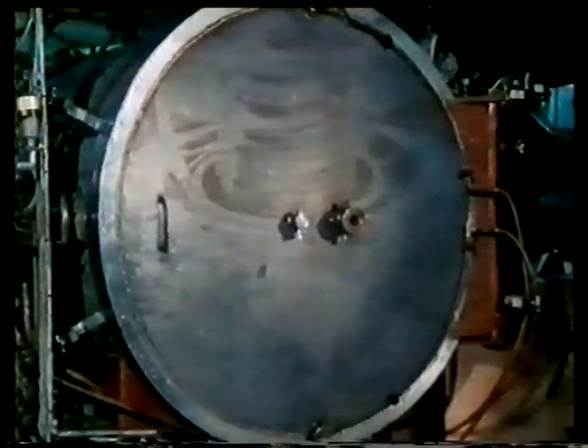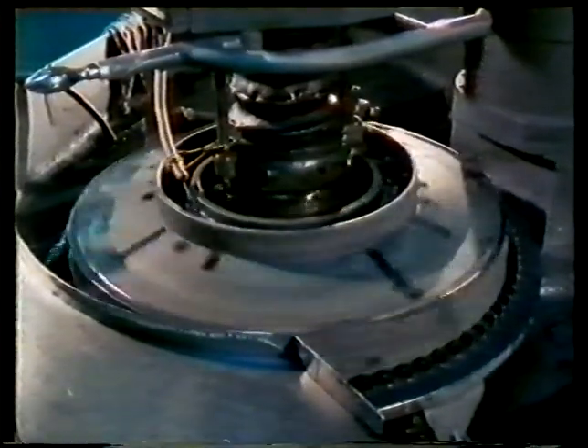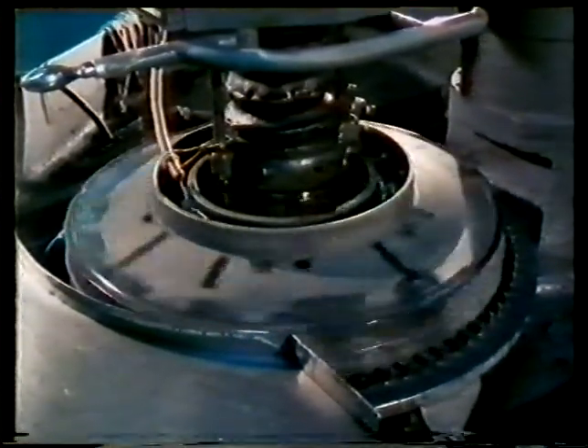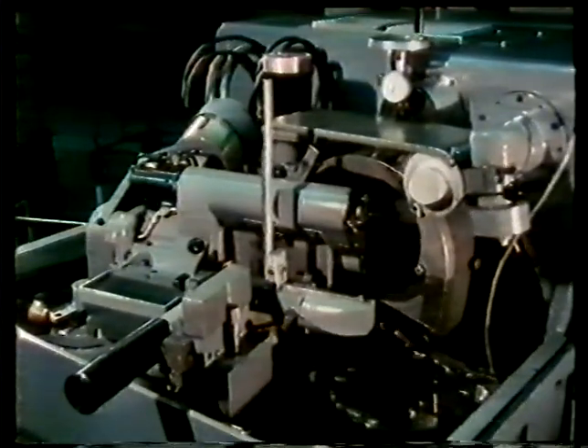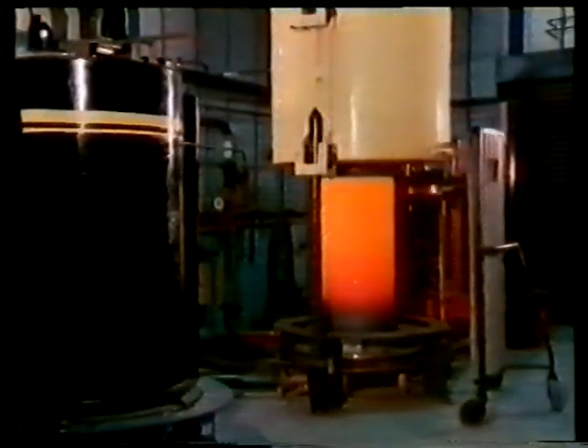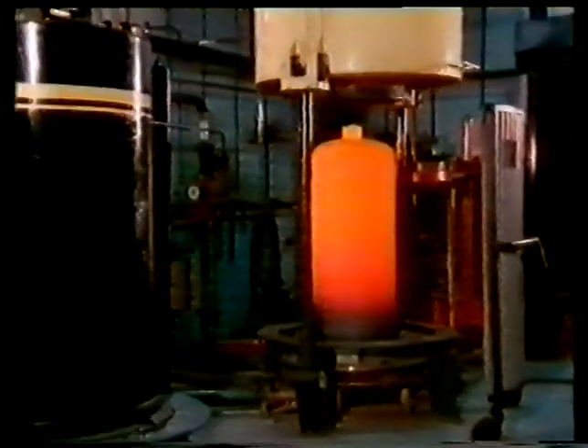Then they go on to a variety of automated grinding processes. These ensure correct geometry of the inserts before coating. In principle, the coating is similar to the one applied to high-speed steel inserts. These days, many of the carbide inserts have a double coating. The titanium carbide layer gets an additional coating of aluminium oxide. This produces a durable cutting edge, which gives almost twice the metal removal rate you'd get from a single coating.